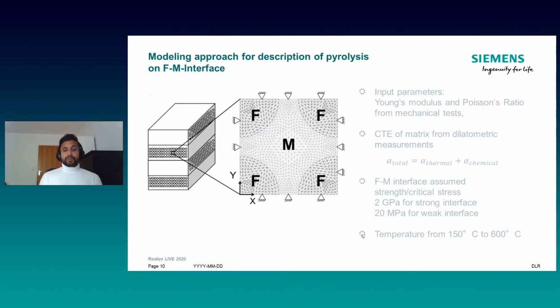Now, since we know that the fiber matrix bonding plays a major role in our microstructure and finally in the properties of our material, we can dig into the modeling and try out different combinations. So in our preliminary study, we derived the thermoelastic properties of fiber and matrix. And in the case of our preliminary study, we just took the interface properties. For example, for a strong interface, we took 2 gigapascal as the strength and 20 megapascal for our weak interface.